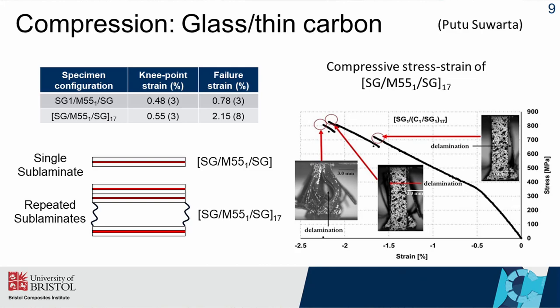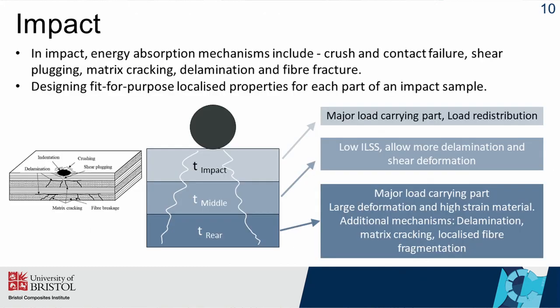You can look at the overall behavior in compression, and this is a specimen with repeated sublaminates through the thickness that has been loaded in compression. You see we have this knee point on the stress strain curve, then eventually we get some delamination and finally a catastrophic failure of the whole specimen. So we've introduced some sort of pseudo-ductility in this response.